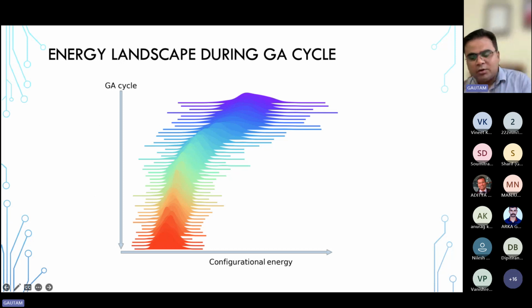Now, why is this working out? When we are running this genetic algorithm, I'm showing you this for just one alloy. As we are running these calculations, from this ridge plot, each plot is for one GA cycle, and it shows the distribution of energies. As you can see, this landscape is changing. As I'm running my GA cycle, I'm finding lower and lower energy configurations. With my GA approach, I'm able to find the low energy configuration faster. And if we do this for candidate crystal structures, the crystal structure which can get to the lower energy faster can have the greater entropy, and hence it can get stable. So that is what we are developing through this particular GA approach.